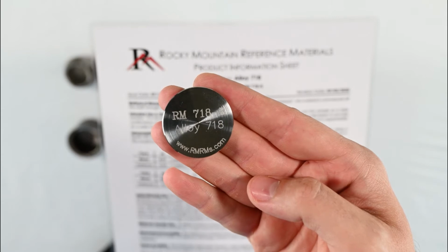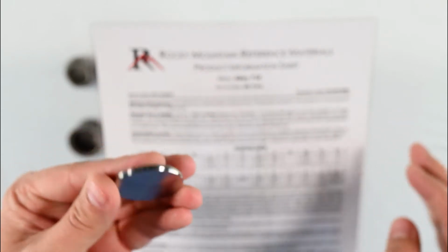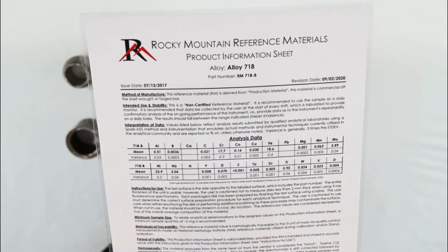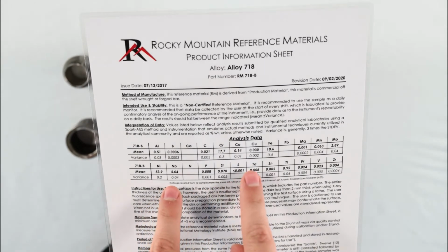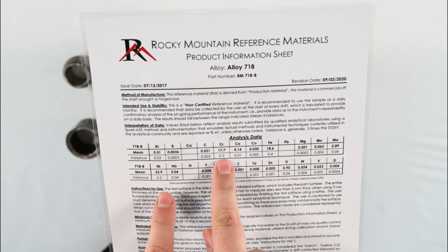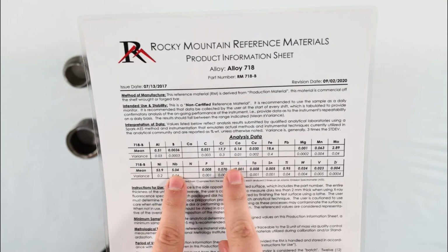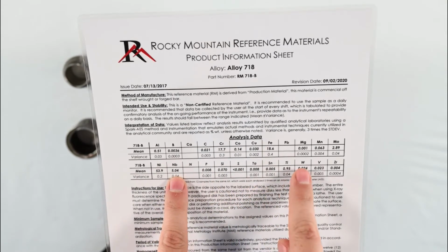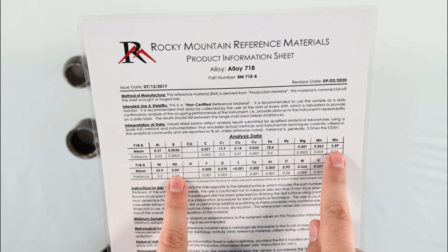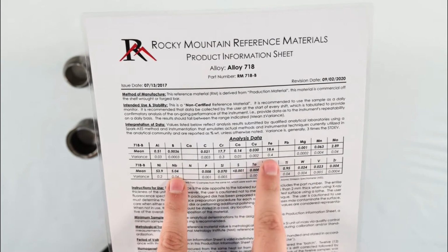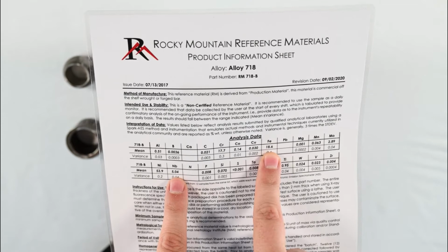Okay guys, so first up is the 718 reference sample. I want to show you the cert for the sample first, which is right here. I just put it on the analyzer so you could see it. Our primary alloying elements in this case are chrome at about 17.7%, niobium at 5.04%, and then we've got molybdenum at 2.89, and then there's a little bit of iron in this alloy around 18.6%.